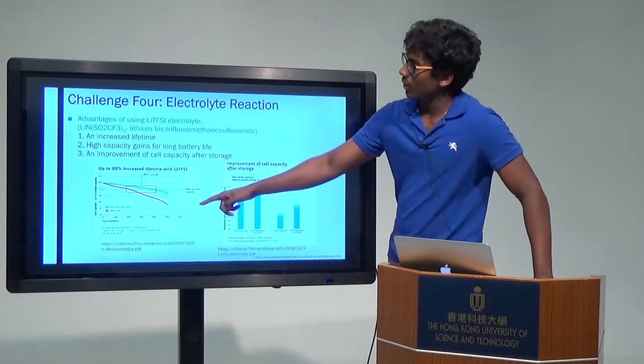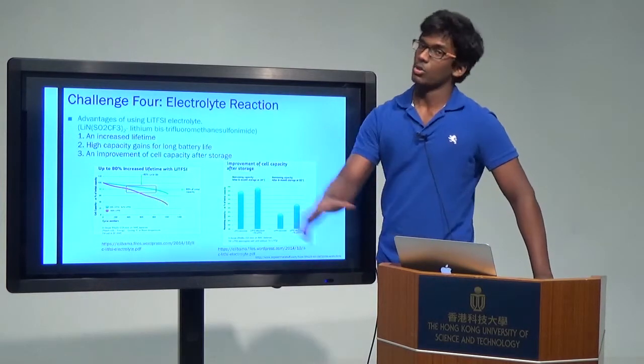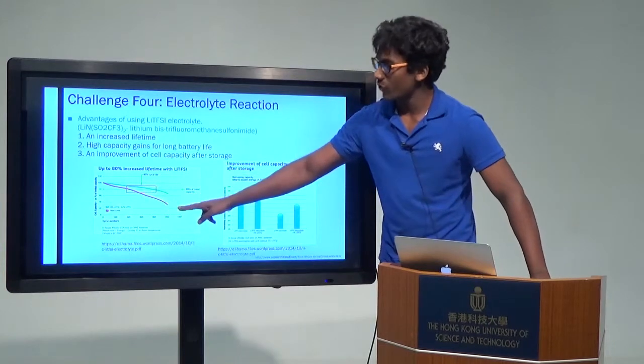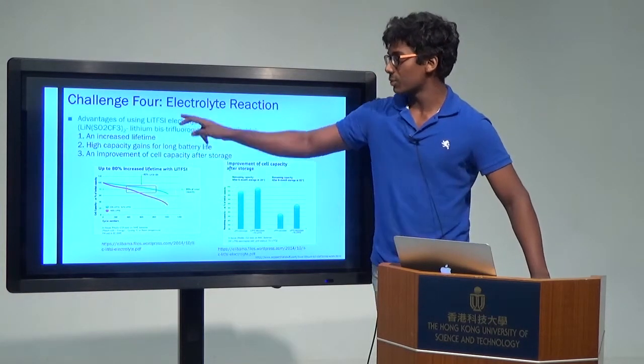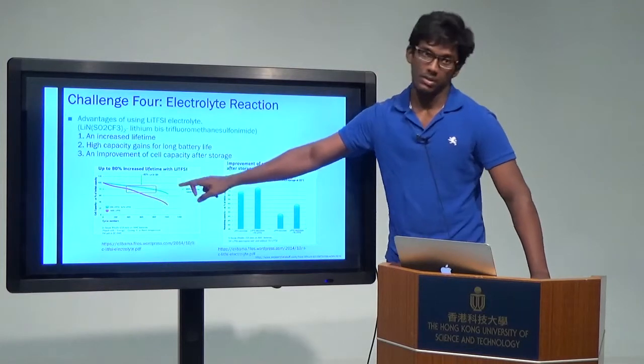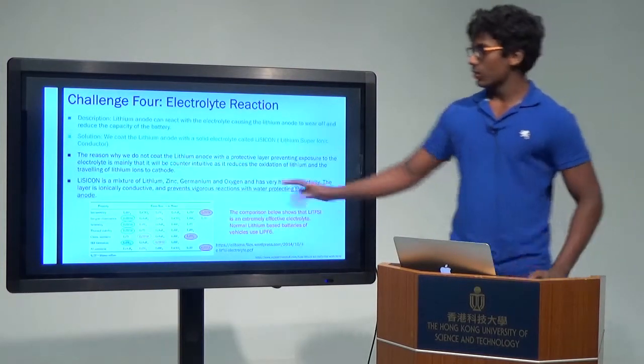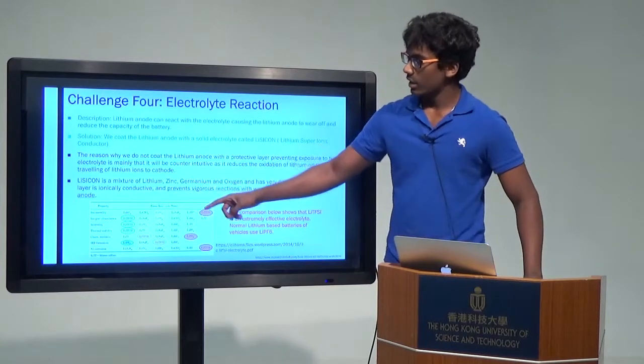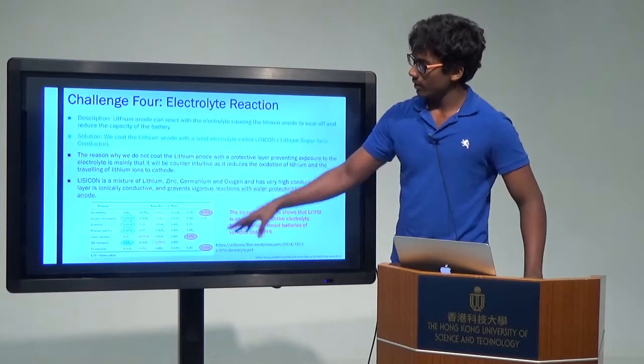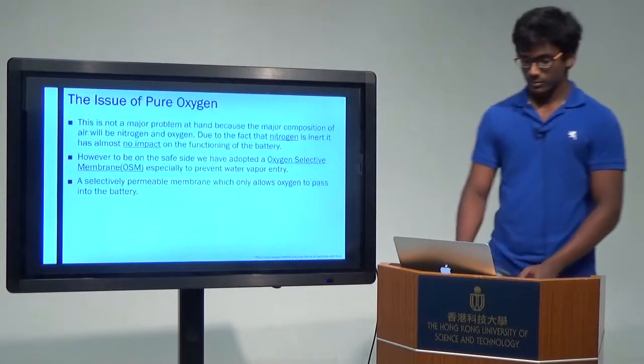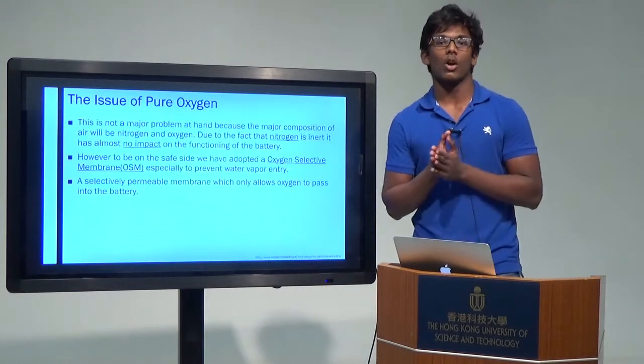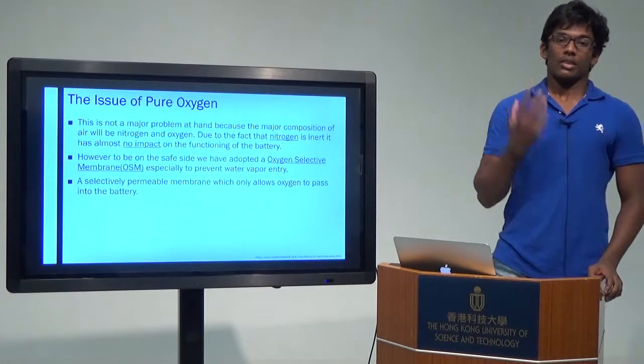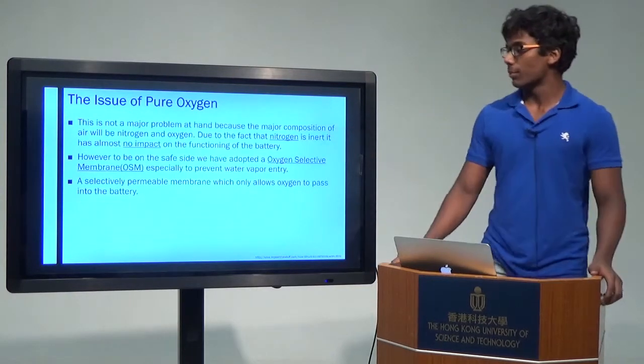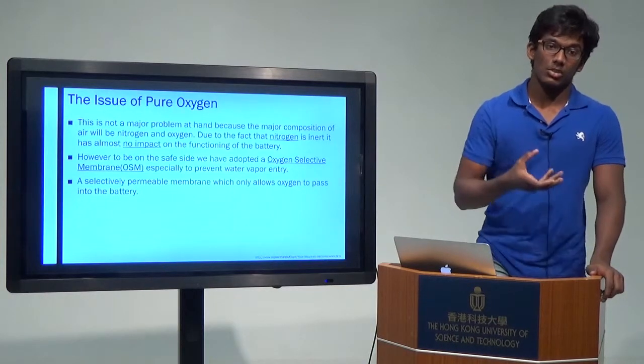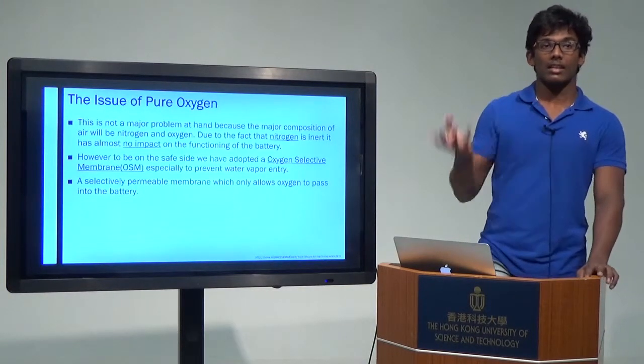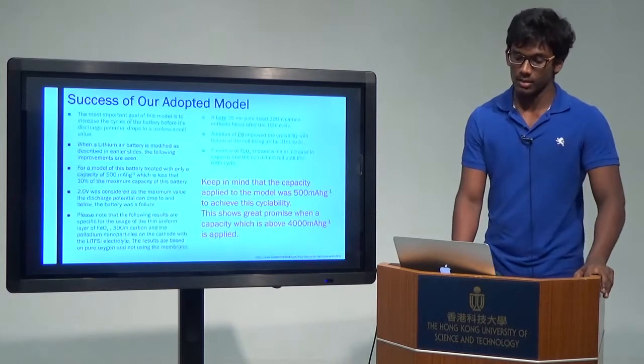As you may see in this graph, this is the normal electrolyte, which is used in current batteries, whose capacity continues to fade. But just by using 30% of this particular electrolyte, it has increased by 80%. And as you may see over here, it surely shows that our electrolyte is far better than all the currently used electrolytes. Another problem is the usage of pure oxygen in our battery. For this, we have adopted an oxygen selective membrane at the point where the oxygen comes into the battery. This prevents water vapor entry and entry of other unnecessary substances.